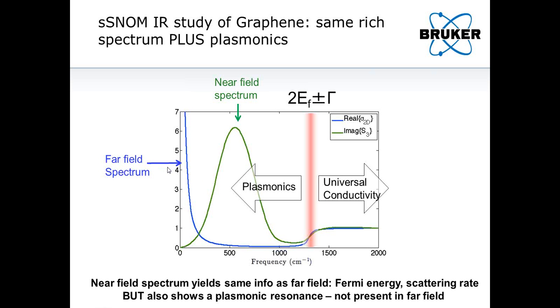For the far-field spectrum, you have k parallel is essentially 0, so you're not able to excite the surface plasmon. But for a near-field spectrum, if the momentum is sufficient, you can see something like this huge hump that I'm showing in this green spectrum. But all the other features would still be there. So you'd still be able to discern the value of E_Fermi. You'd still be able to figure out gamma, because you still have this transition into the universal conductivity regime that occurs at basically the same frequency.